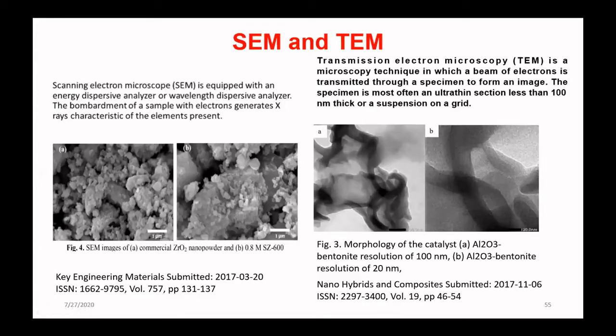So using this instrument, we can observe whether there is destruction of the materials or not. For example, in our experiment, published in Nanohybrid and Composite, we can see that there is no damage to the structure of the clay after pillarization. The layer still exists.